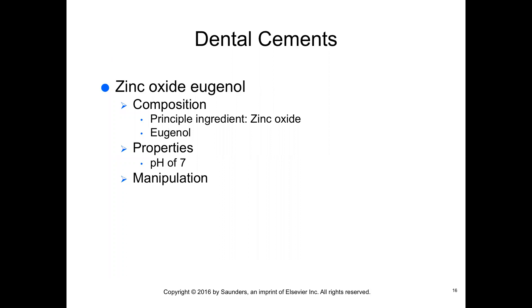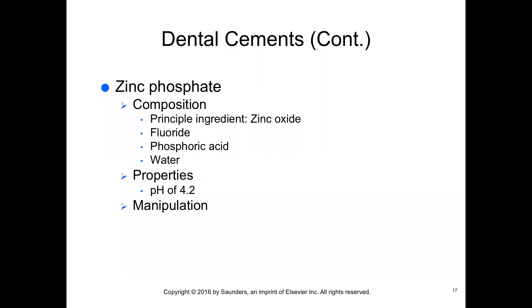Eugenol has long been known for its sedative effect on the pulp, largely caused by its antibacterial effects, though it can be irritating when in direct contact with the oral mucosa or the pulp. When mixing, equal lengths of accelerator and base paste are placed on a proper mixing pad or glass slab and mixed until a uniform color is achieved. If the powder-to-liquid form is used, the powder is incorporated into the liquid until the desired consistency is achieved. Be sure to wipe clean the surface of the glass slab and spatulas, as these cements are very difficult to remove.